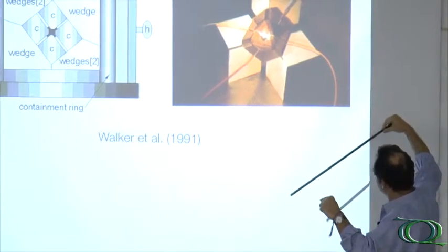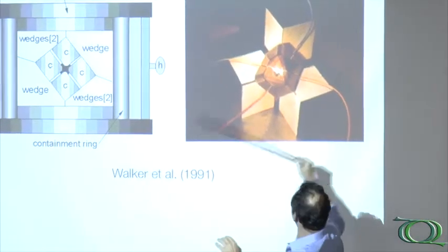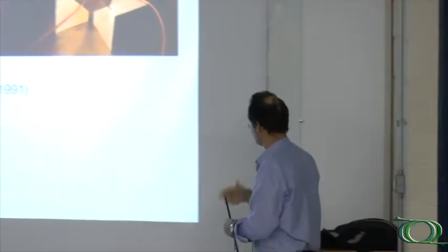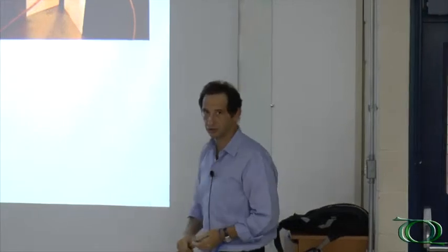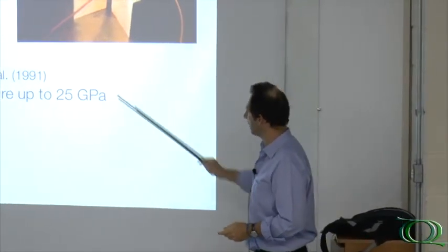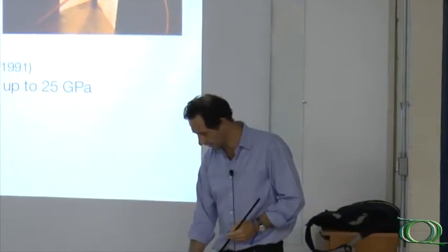You have an octahedral cell, so you have eight faces. You can distribute very uniformly the force. Basically this is hydrostatic pressure up to 25 GPa, which is very interesting also for geophysical studies.